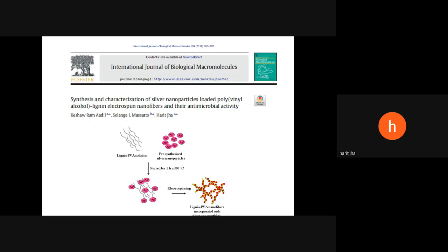Yeah, this is the overall outline of how exactly the process was carried out using electrospinning. We combined the lignin PVA solution with pre-synthesized nanoparticles, which was stirred for 1 hour at 80 degrees. The best part with lignin is that it does not allow agglomeration of the silver nanoparticles, which is a major issue with these metal-based nanoparticles. The agglomeration leads to their conversion into macro-sized particles and losing their quantum effect.